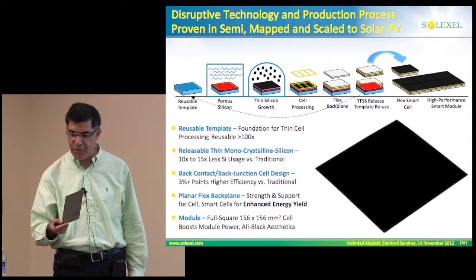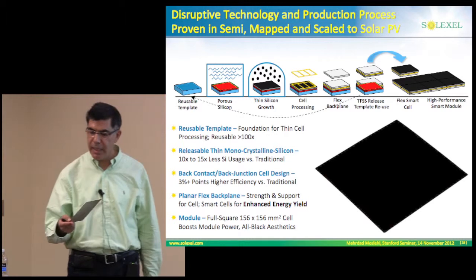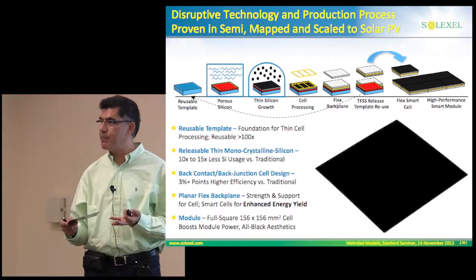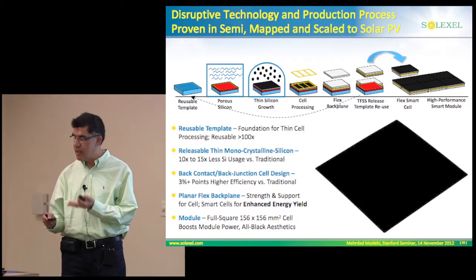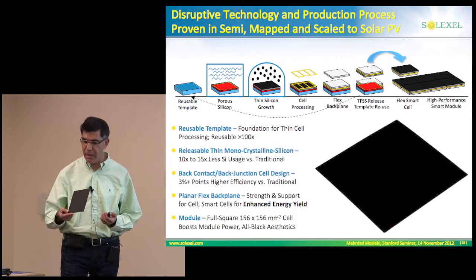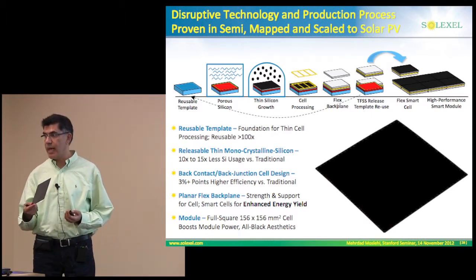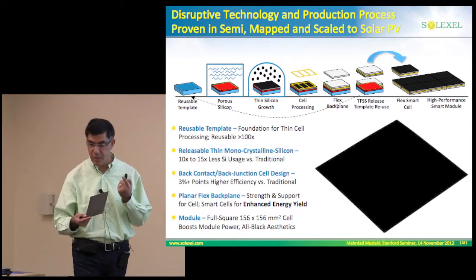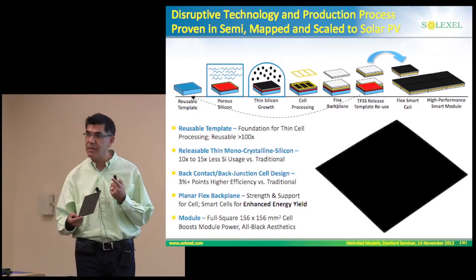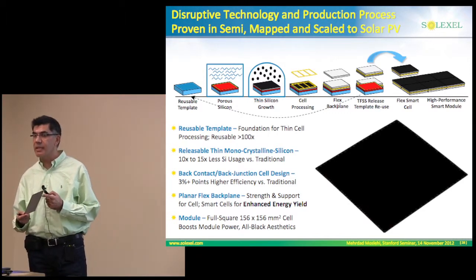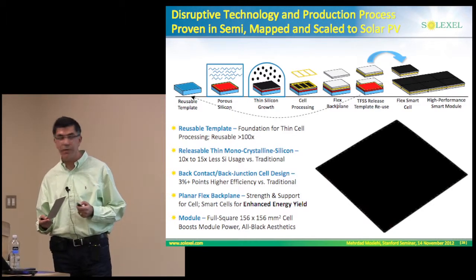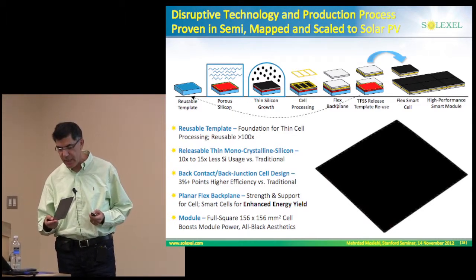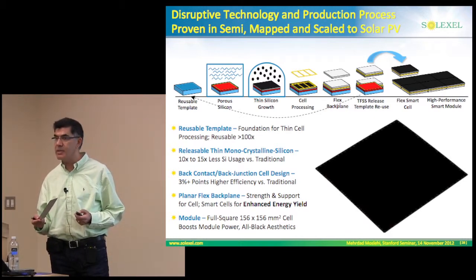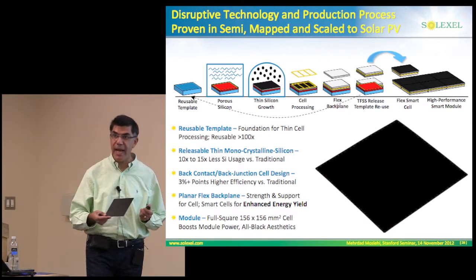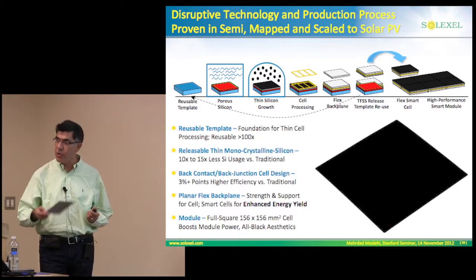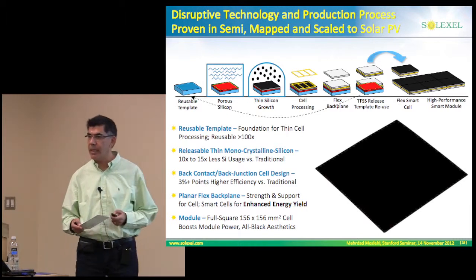Next step, we actually form a porous silicon layer on the surface. It's really a surface modification process where you create nanopores. We have a controlled porosity profile over the wafer. This porous silicon has two important functions. One is it's an excellent epitaxial seed layer, and also it's an excellent release layer when we are ready to do the liftoff. So the next step, we grow our thin silicon using atmospheric pressure epitaxy. And this is in situ doped. We actually program the doping in situ.